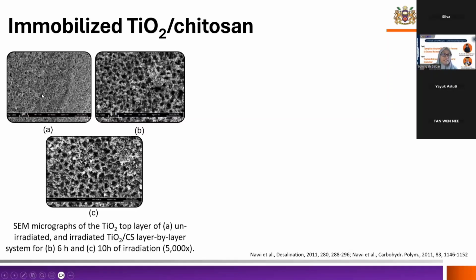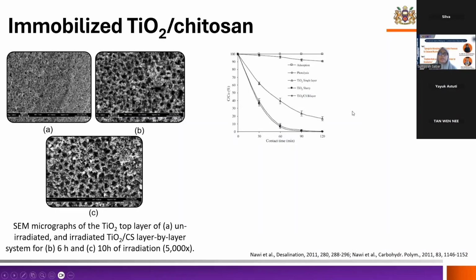Okay, so you can see the difference in the SEM images of the layer. This is the top layer, the titanium layer, without any irradiation, the initial surface of the titanium dioxide. This is after 6 hours, and this is after 10 hours of irradiation. You can clearly see that there are micropores forming on the titanium dioxide. When these pores are formed, it allows better diffusion of the pollutant and also light penetration to the chitosan.